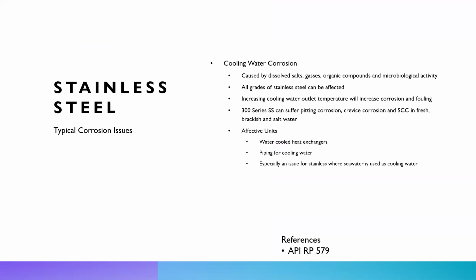So another issue you can have with stainless steel is just your typical cooling water corrosion. This can happen to all grades of stainless steel, just because you're going to have chlorides in your cooling water. You're going to have dissolved salts, gases, organic compounds, and even microbial activity, which can lead to MIC, microbial influenced corrosion. So increasing your cooling water outlet temperature will increase corrosion and fouling. Fouling is another issue you're still going to have with stainless. And also 300 series stainless steel can suffer from pitting corrosion and crevice corrosion, especially in salt water, seawater, and brackish water, which is a lot of what we see in the field.